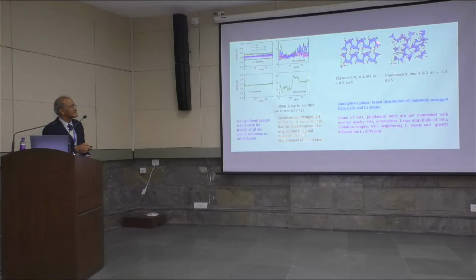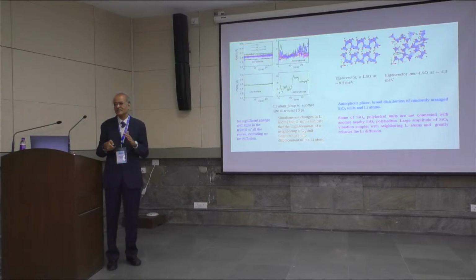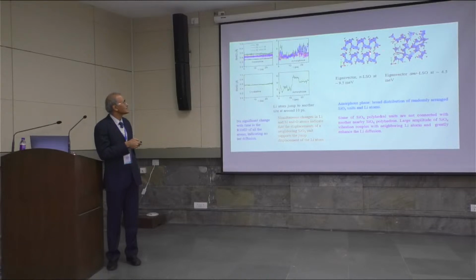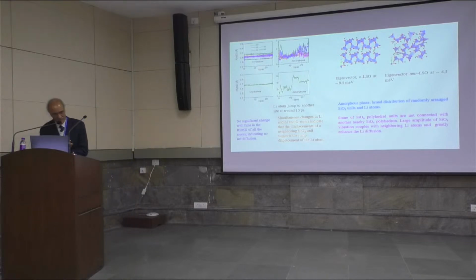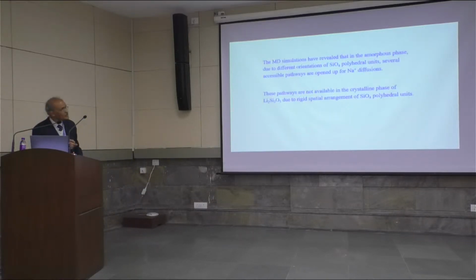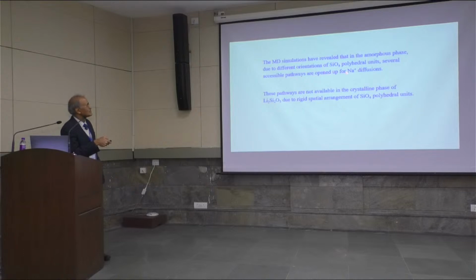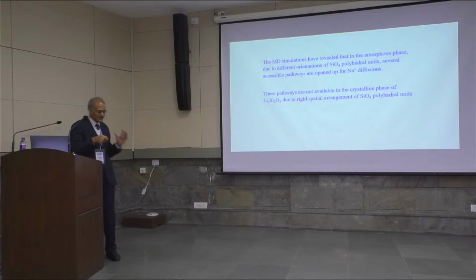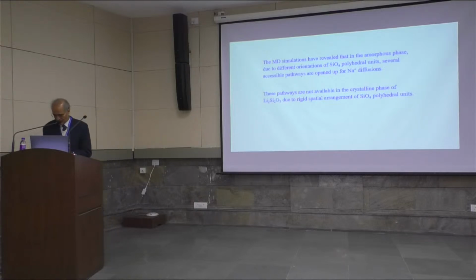And if you do the lattice dynamics calculations where you can calculate the phonons and phonon eigenvectors, then you can identify specific phonon eigenvectors for different phonons, to see what kind of dynamics is taking place. Okay, so what we have learned from this essentially is that the molecular dynamic simulations revealed that in the amorphous phase, you have different orientations of these silicate polyhedra, and there are also several accessible pathways opened up for sodium diffusion. This is not available in the crystalline material due to definite fixed orientations, so we are not able to see it.